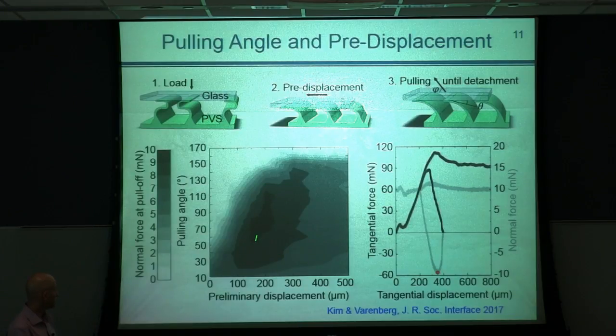And we also found that the best results are achieved when preliminary displacement is equal to half the distance needed to start sliding, so somewhere here, which can be explained in the following way. When the preliminary displacement is not large enough, then all these projections are not aligned well, and they do not perform efficiently. When preliminary displacement is very high, then sliding starts, which means that each of the structures starts sliding, sticking, and sliding, and they are all stressed to a different extent, which again results in non-uniform, not efficient performance. However, somewhere in between, there is an optimum range when the forces are maximum.